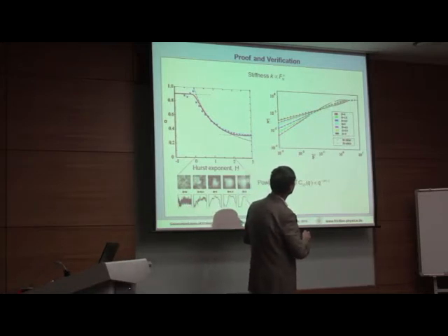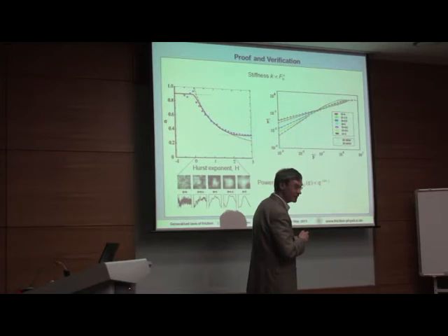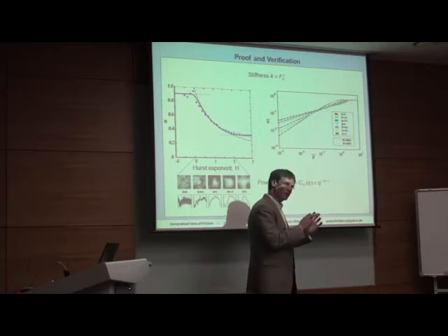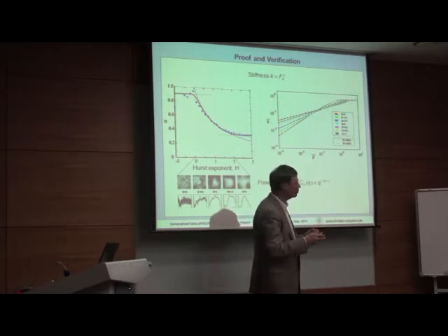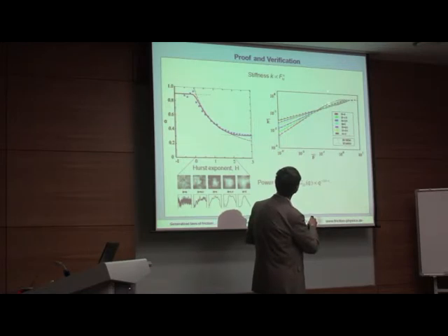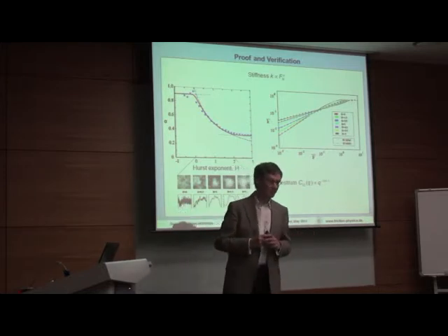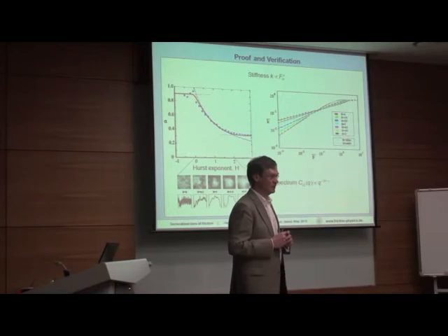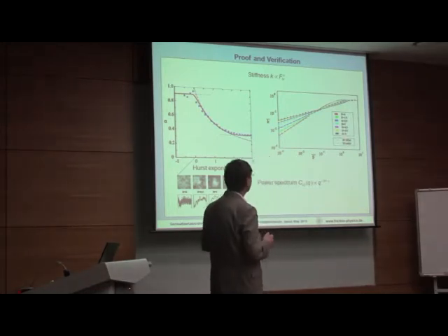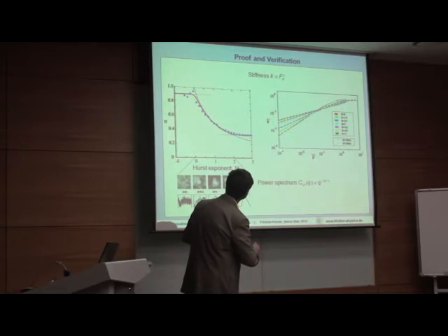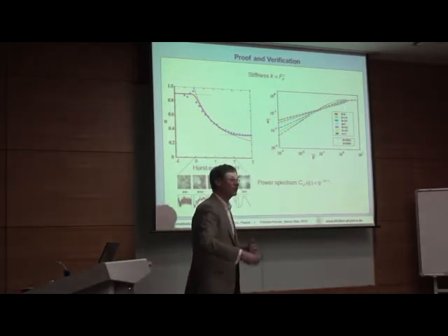The only place where it is not guaranteed that they are exact is the intermediate region. For Hurst exponents in the typical range, 0.5, 0.7, 0.8, you also get an almost completely correct result. And for very small Hurst exponents, there is an error of about 20%. So these are forces from 10 to the minus 3 up to complete contact.